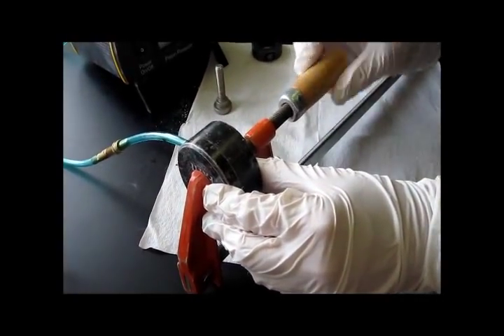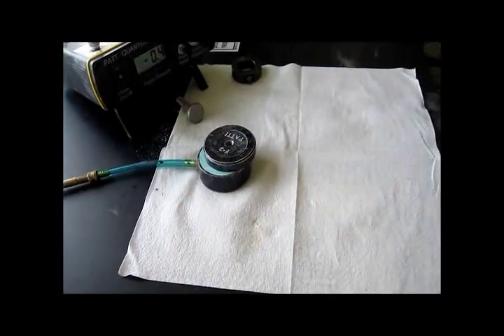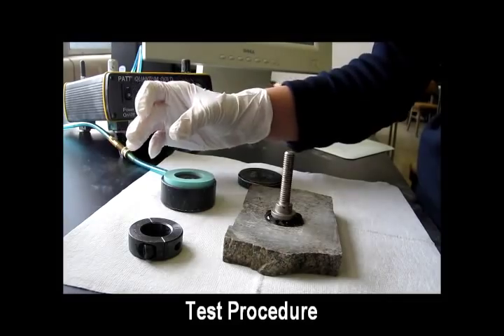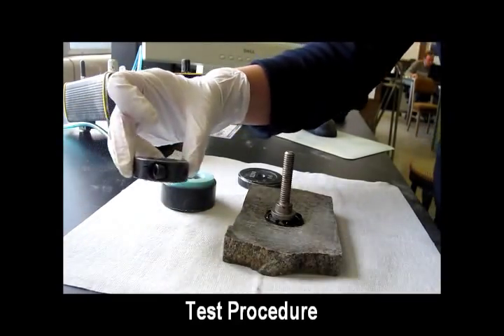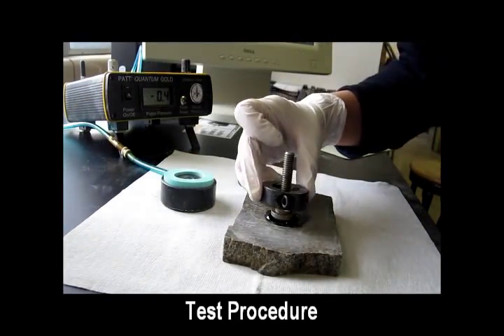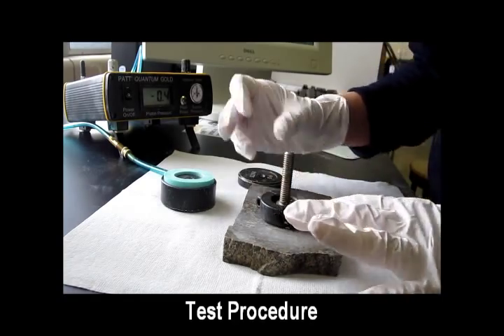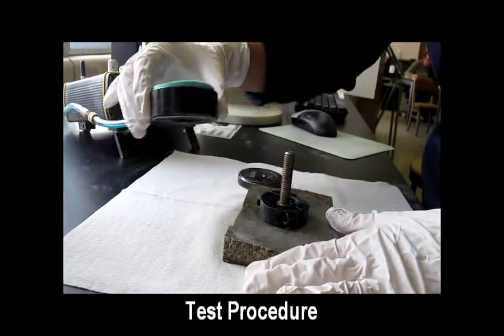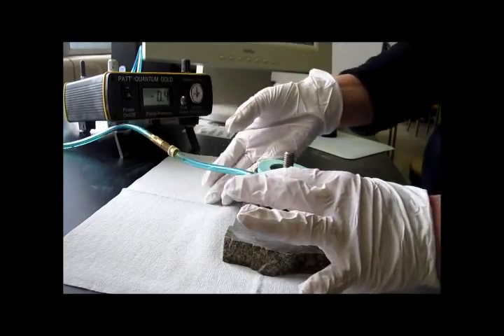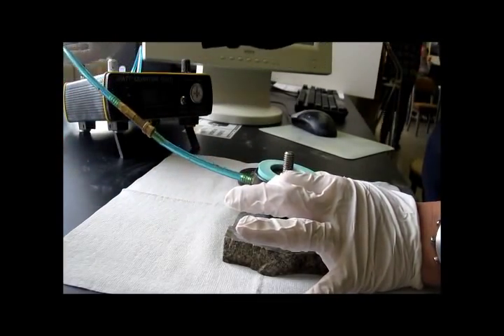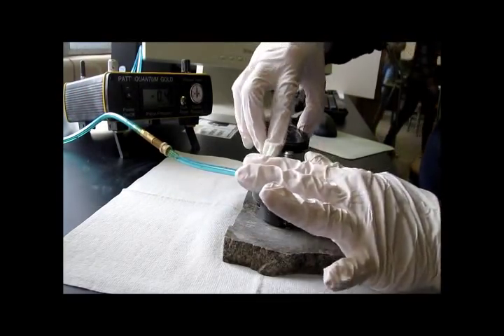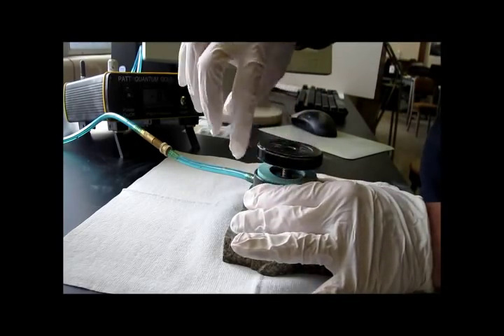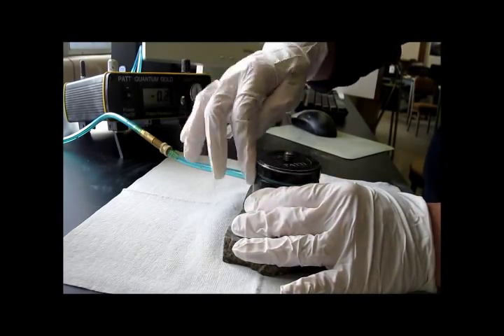After loading rate calibration, the assembly is removed from the clamp. To run the test, place the ring support concentrically around the stub to reduce the possibility of eccentric loading. Carefully place the piston around the stubs and on the support ring without disturbing the stub or inducing unnecessary strain in the sample. Screw the reaction plate into the stub until the pressure plate just touches the piston.